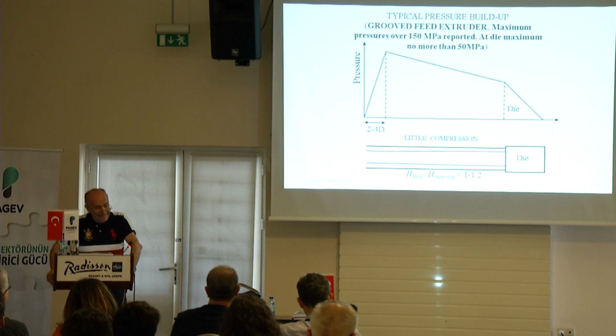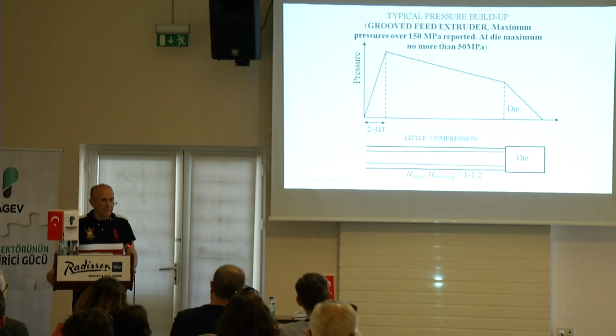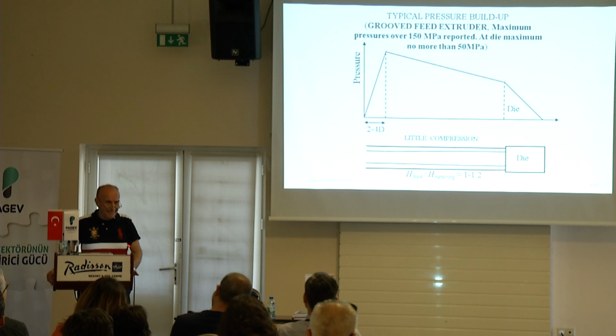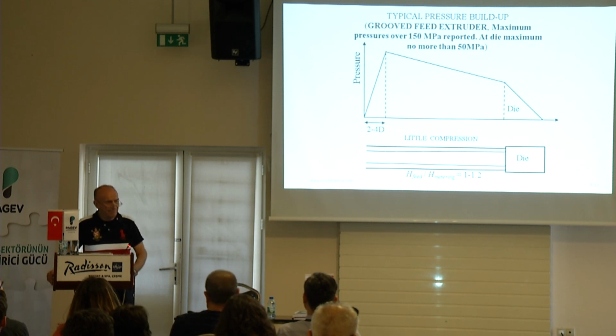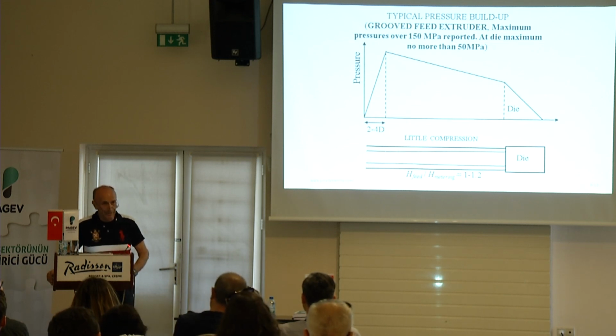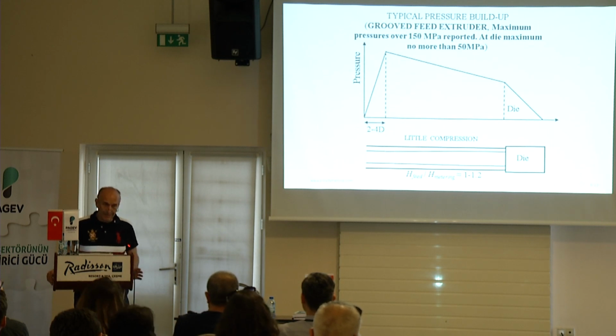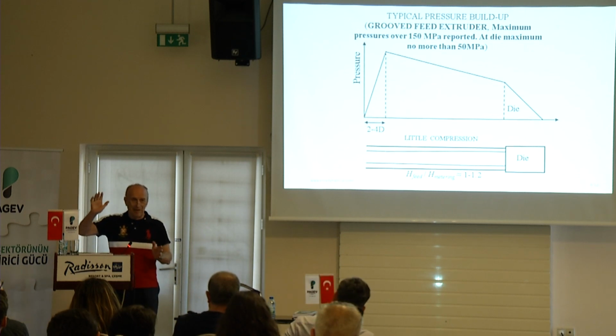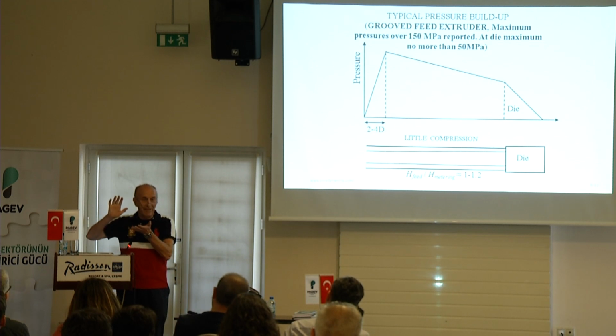And the pressure is very large, and you may really have problems, and it's rather difficult to design groove-feed extruders. Everybody can design and build smooth barrel extruders. It's not a complicated machine. You can buy a screw from somebody or design it and fabricate it yourselves. But when it comes to groove-feed extruders, it's complicated. Yes, in Turkey, I have contacts with one company that produces groove-feed extruders. They're very good. They pump out a lot of material because you really build up a lot of pressure. We're talking about 150, 200, and this pressure is pushing the polymer out.